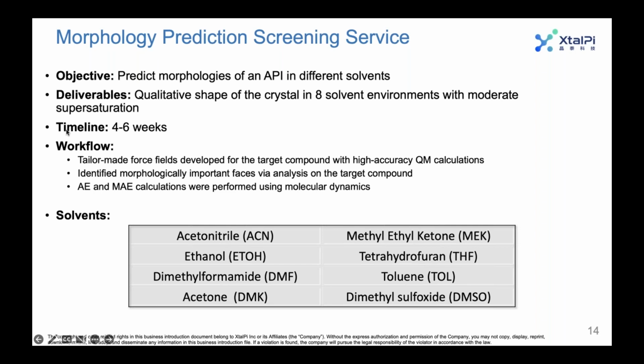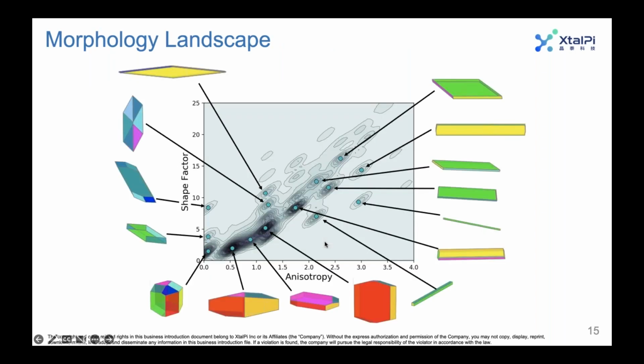The workflow for this particular project started with tailor-making the force field, which was developed specifically for the target compound using high accuracy quantum mechanical calculations. We identified morphologically important faces for the target compound, and then we used attachment energy and modified attachment energy calculations with molecular dynamics. And these are the 8 solvent systems that we considered. So this is the morphology landscape.